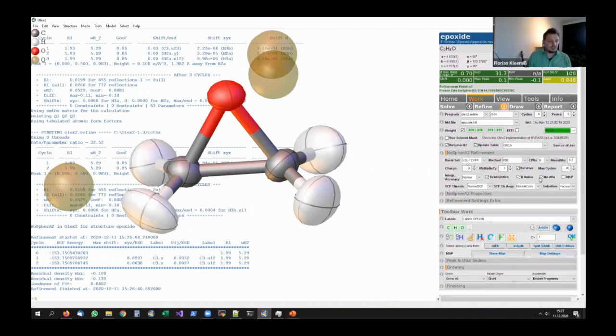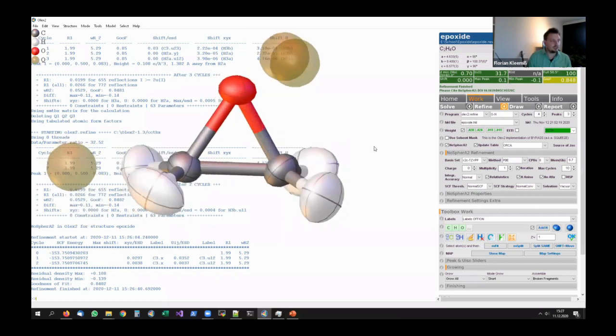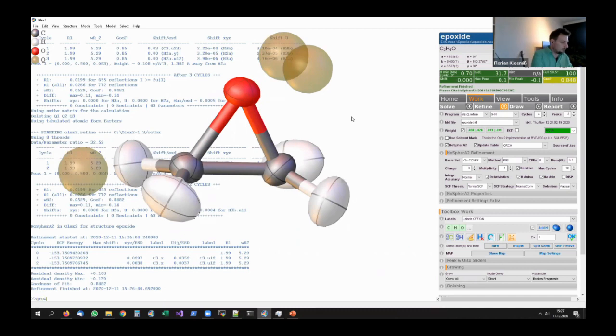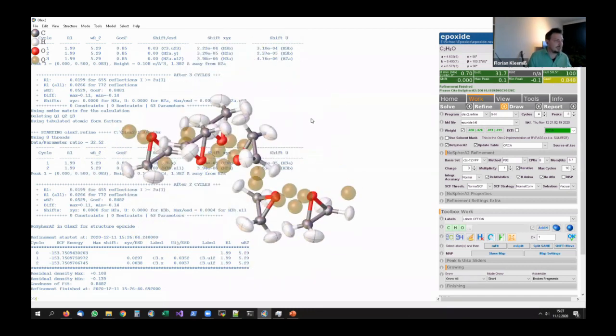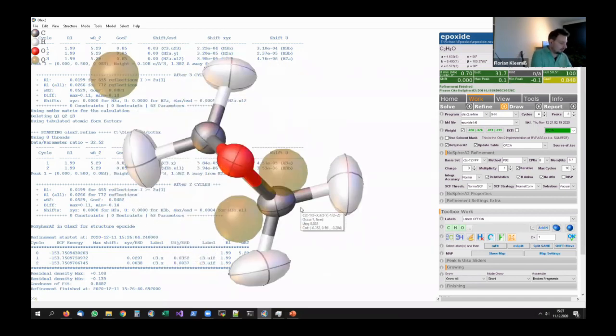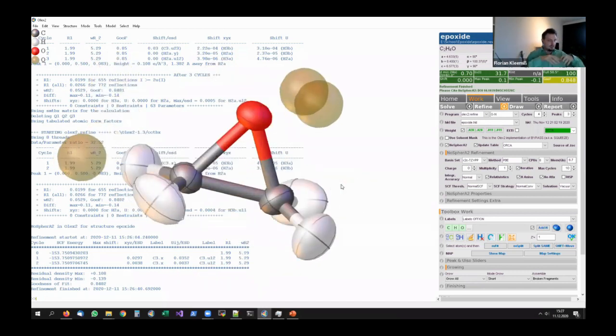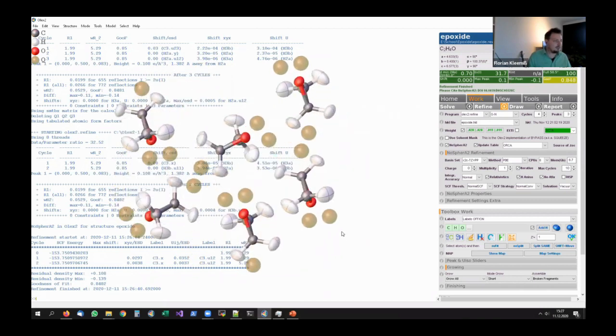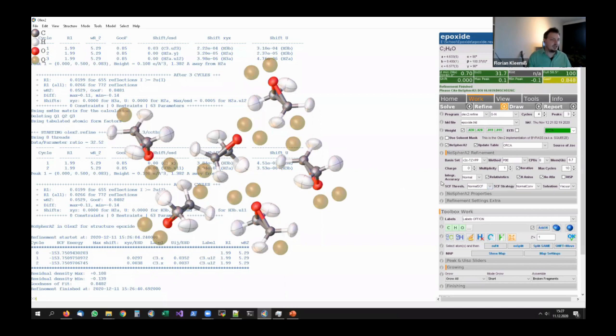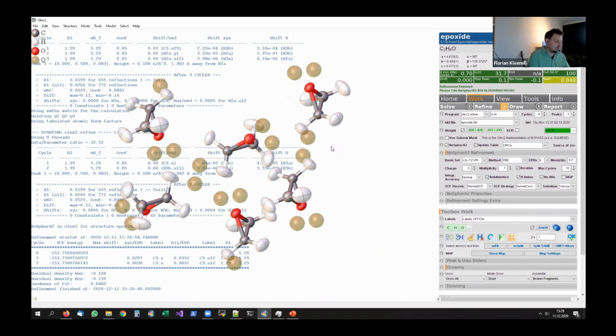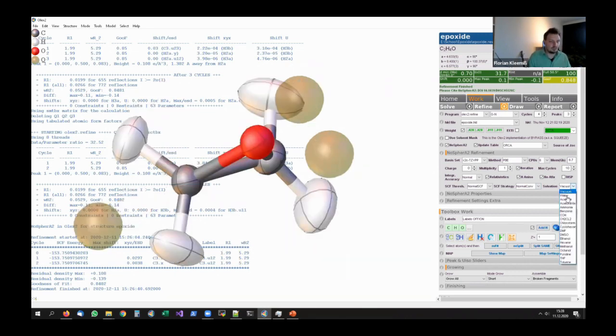A second thing, which is still rather new, is the use of solvation models. If you think about it, we are now doing a calculation of this molecule in the gas phase. But in a crystal, you usually have neighbors to the molecule, as I show here by growing the crystal. One thing we can do is include a whole lot of molecules that surround our central molecule to explicitly calculate the wave function for all of them. But as you can imagine, the more atoms we have, the more time we need to invest into the wave function calculation. So if I calculated this, it would take much longer than the calculation of the small fragment. This is why we can use solvation models of a few selected solvents to already polarize our wave function without the cost of additional atoms.